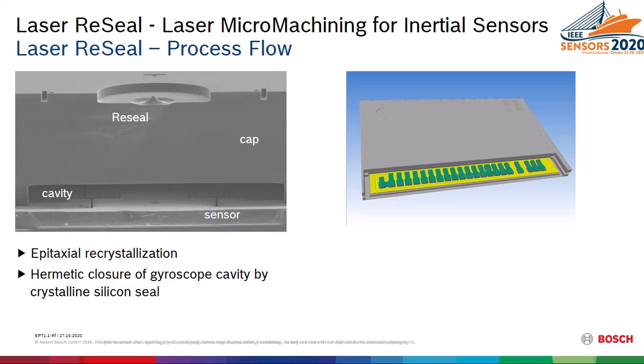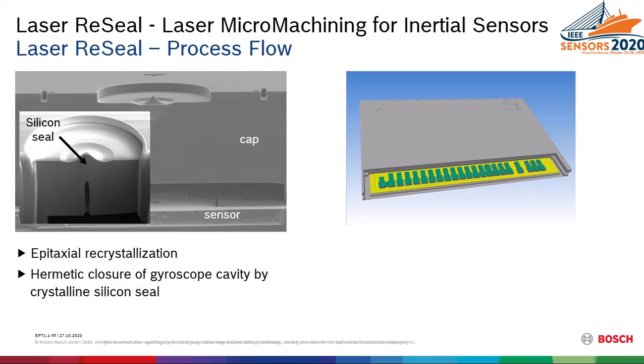So below you see the sensor, and above there's the cap layer, and in the middle there's the laser reseal. And in the insert it's shown that it's really perfectly seamlessly closed and you get an epitaxial seal of the vent hole. The whole process takes about 1 millisecond.